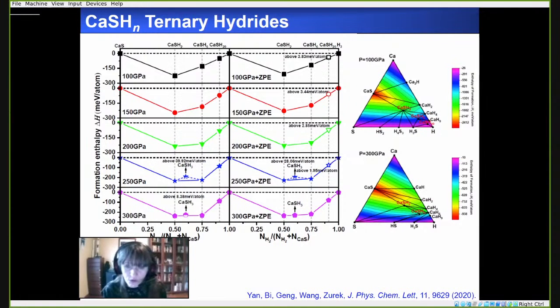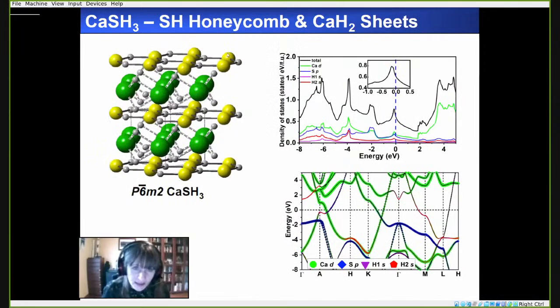Now, most of these phases, unfortunately, were not interesting for superconductivity. They were not metallic. The only one that was interesting was the CaSH3 phase that I mentioned right here. And what was really interesting about it is that it was comprised of these types of honeycomb lattices of sulfur atoms bonded to hydrogen. So in a way, this is a two-dimensional version of the SH3 structures that has previously been found to be superconducting. So it's a two-dimensional version having these types of honeycomb nets separated by CaH2 layers.